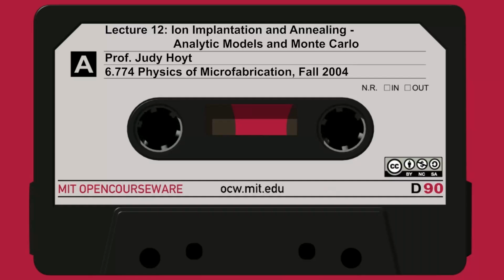Imagine we have a surface of a silicon wafer, so the silicon's on the right here. This is the interface with a vacuum, and on the left is a vacuum. And you have a beam of ions coming in, in this case right in this red spot. Any given ion that comes in is going to experience a series of collisions, and in fact many of them are billiard ball-like. It's going to have a series of collisions with atoms in the substrate. You can see it's having little collisions here and there. It loses energy as it goes in via these processes, and eventually comes to rest at some point here, shown by this little blue dot.